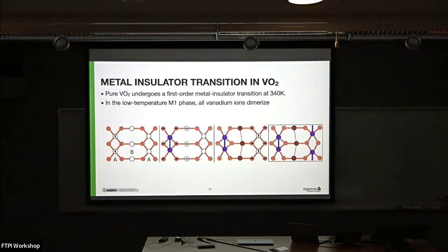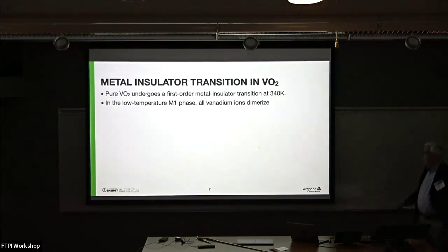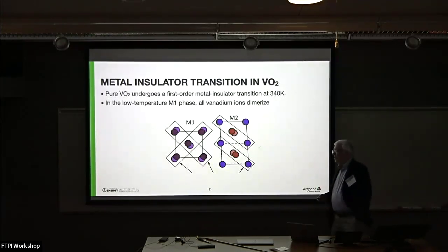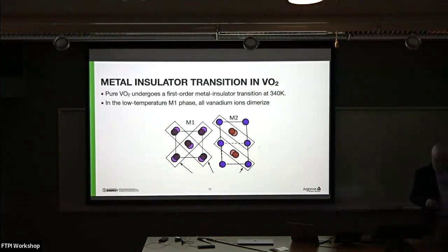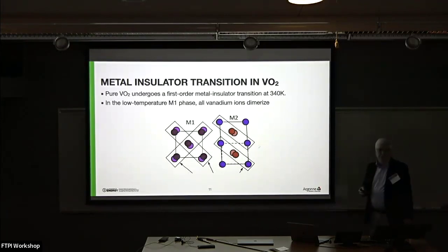What happens is there's a dimerization of neighboring vanadiums here. That forces out this oxygen, which creates a buckling of the neighboring chain of vanadiums. And then that pushes this oxygen in, so you still get dimerization here, but it's out of phase. So you have this alternating dimerization, buckling, dimerization. But in pure VO2, that happens simultaneously along two directions, 110 and 1-10. And that means that actually every single chain is both dimerized and buckled.